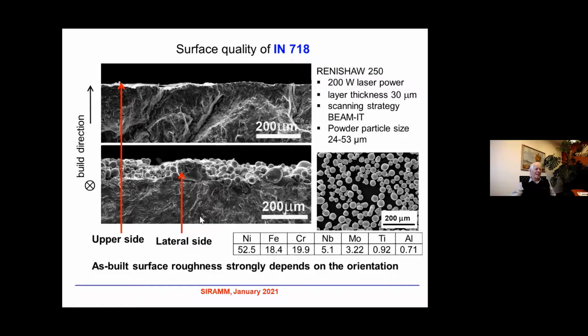The lateral side of the specimen you can see here, and if the crack started on the lateral side, there are many problems with notches here. You can see here unmelted particles. So such a surface is, from the point of view of initiation of cracks, much worse than this one. So the as-built surface roughness strongly depends on the orientation. So please remember this statement.